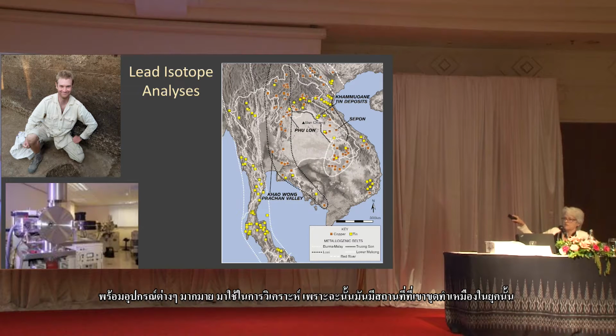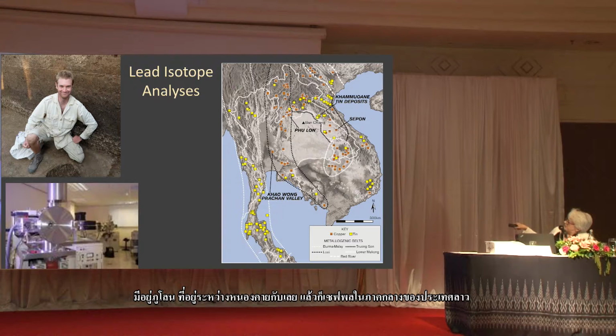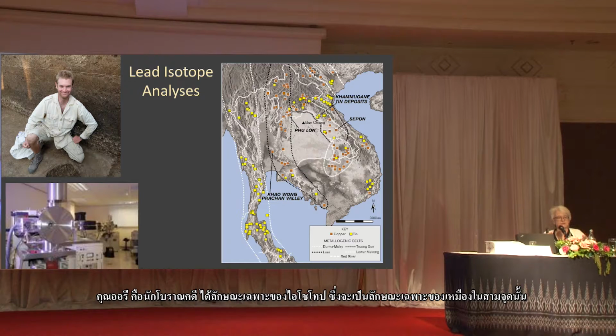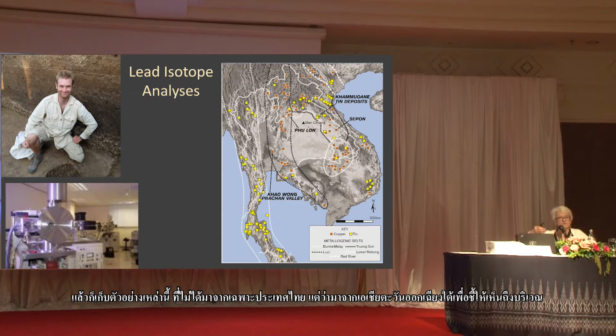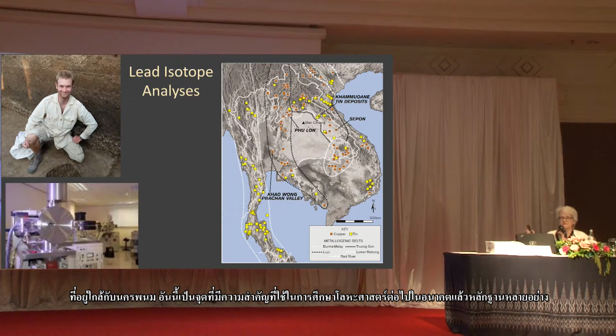Okay, so there are 3 mining or metal smelting sites or regions that have had some study that were used during prehistoric times. We have the Khao Wong Prachan Valley in Lopburi. We have Phu Lon, which is at the border between Nong Khai and Loei. And we have Sepon in central Laos. So Ollie was able to get signatures of the kind of lead isotope signature characteristic of those three mining sites, and then compare it with our sample and many other samples, not only in Thailand, but in Southeast Asia. While we're looking at this, I just want to point out the Khammouane tin deposits, which are in Nakhon Phanom. These have not been studied, but I think this is a very high priority for archaeometallurgy going forward.